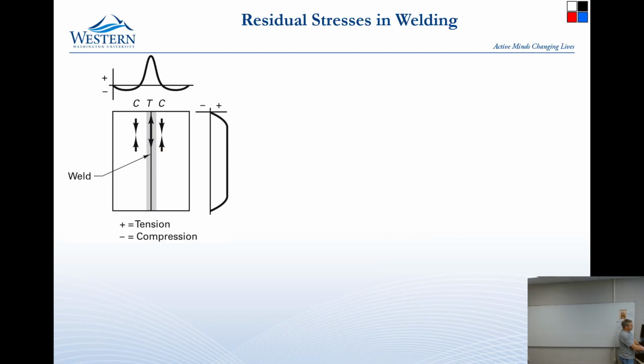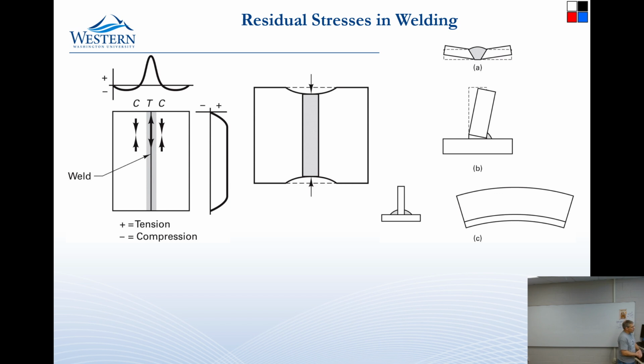When you do this, you get all kinds of residual stresses because you weld along the seam and then it cools. When it cools, it will shrink. It's pulling on all the material around it, so it's in tension. The material on each side of it is in compression, because the weld is trying to make it shorter, so it's trying to compress everything on the side. And what this will do is cause your part to change shapes. It will either bow or potato chip or lean or do something to change shapes.